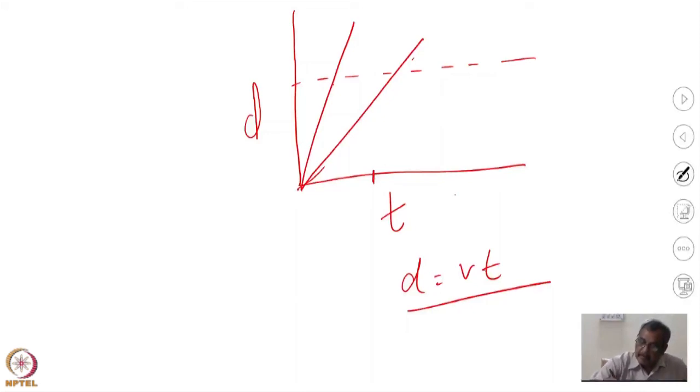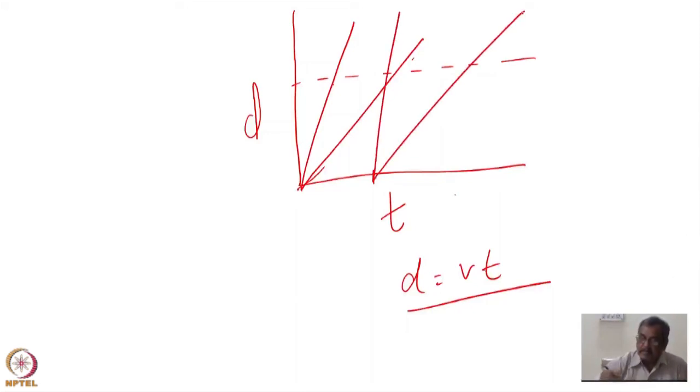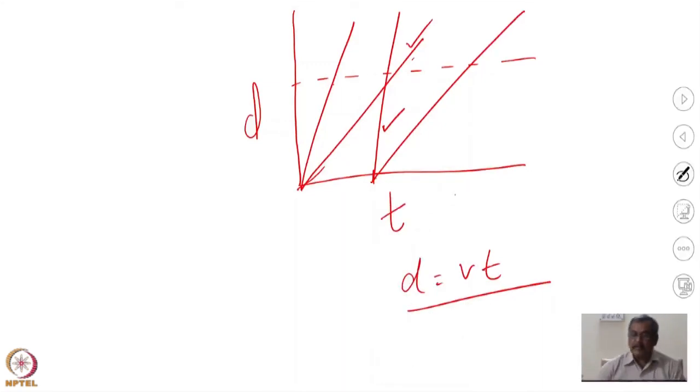Again, I have the same band. It goes like this. But now imagine this one, and this one. So the slower neutron of the previous pulse is taken over by the faster neutron of the next pulse. This is like you might have seen sometimes that in a race, some competitors are lagging by one full lap. And because it's going in circles, you don't know whether he is first or he is the last, because you see the other competitors moving with him, and it's very difficult. So this is known as frame overlap.